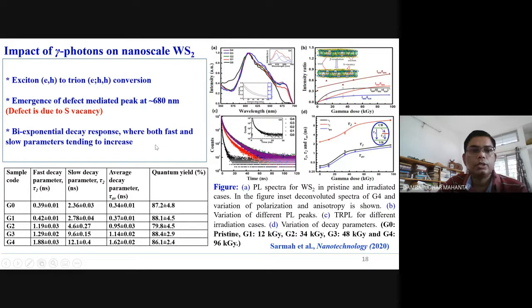So we have bi-exponential decay response of individual peaks, where both fast and slow parameters appear. So the fast parameter is direct radiative recombination between the conduction band electron and the hole present in the valence band. So this is fast emission. And if it is coming through some trapping sites, then we say these are slow parameters. So both are actually increasing. However, quantum yield remains almost constant. It's not changed much. In case of only G2, we found around 80%. And there is no significant change in these cases in quantum yield.